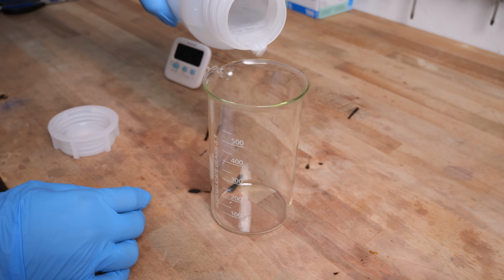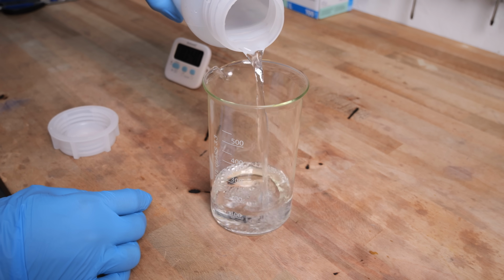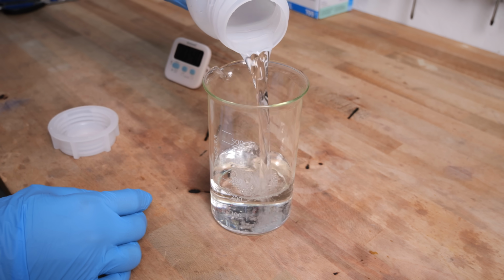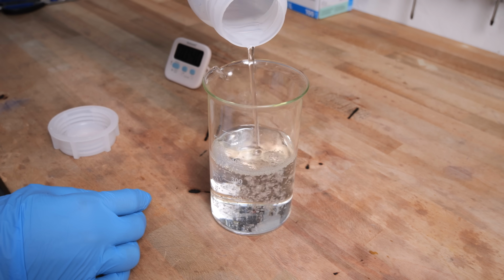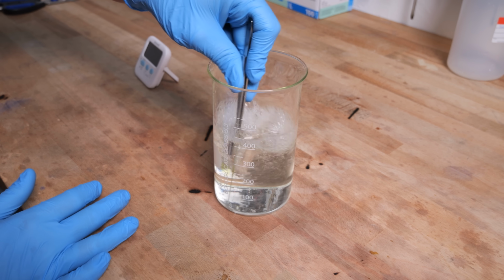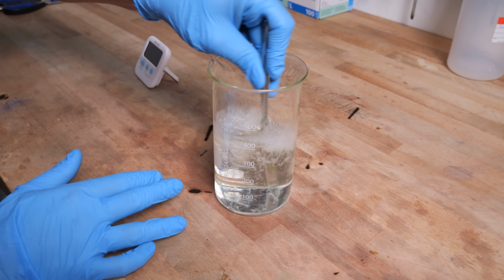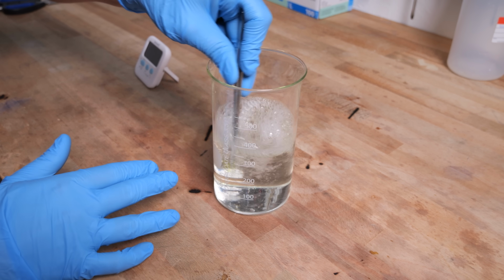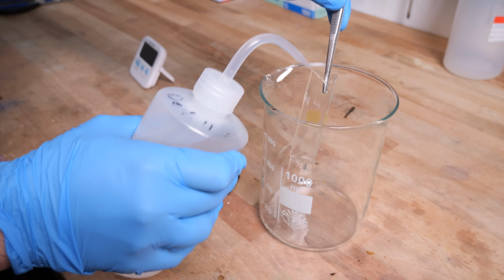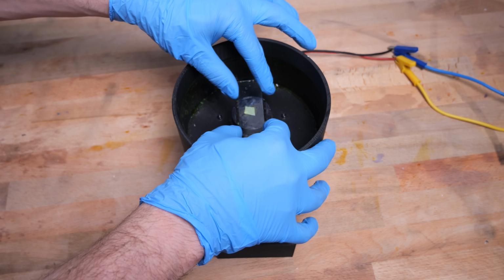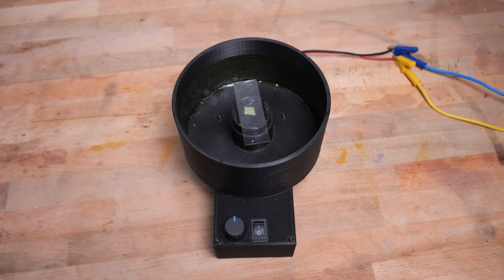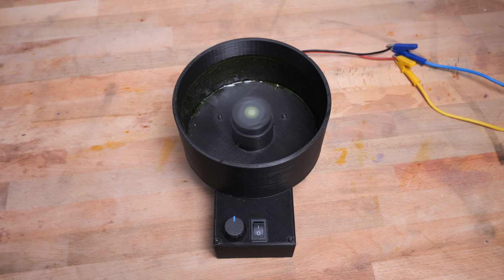As my developing solution, I'm using a 5 gram per liter sodium hydroxide solution in distilled water. I am moving the microscope slide around in the developing solution for 40 seconds to remove all of the non-exposed photoresist. After that, I'm rinsing it with distilled water and put it on the spin coater for a few seconds to remove most of the water before drying it with a hot air gun.